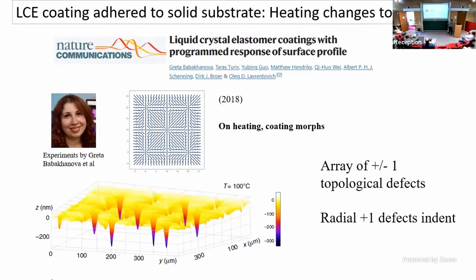So what they did is they made liquid crystal elastomer coatings with disclinations in them. So topological defects, in this case, poking through the thin film. If you look from above, you would see something like this. This material has the same pattern on the top and the bottom. You assemble it, you cross-link it, and then you take one piece of glass off. And so the director is uniform through the thickness. And then she heats it.